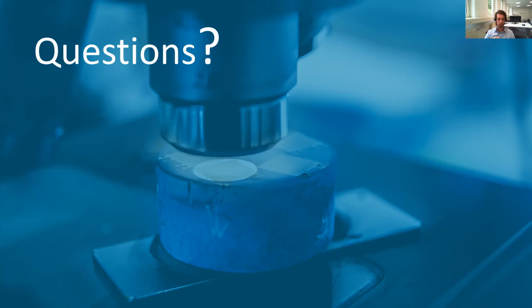From what we've looked into, melt pool monitoring is most likely the best thing. It creates really complete output. After your print job, you can even have a thermal history of your print, which in the future you can maybe also couple with simulation, because then you can simulate what you're not actually seeing. With melt pool monitoring, you're visualizing one layer, you can look at the temperature and a lot of other things, and you could couple this with simulation and look below there. So just to answer your question, no, we've not considered anything else for inline, in-process inspection so far, because this is most likely the best thing.